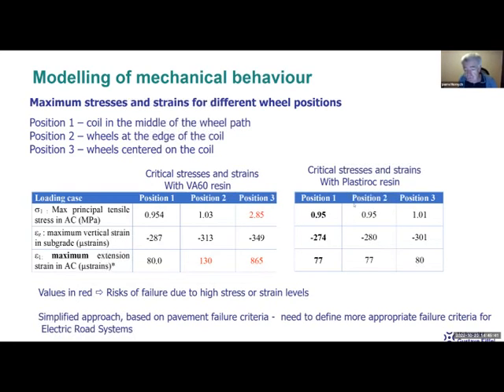So in fact, to reduce the deterioration or to reduce the impact, it is necessary to have materials which have properties which are as close as possible to the asphalt layer. If you have a very soft material inside the pavement, you will create distresses. And again, I think if you have a very stiff material like concrete, you will create distresses. So it's a simplified approach, but it gives a first idea of what happens with different materials.